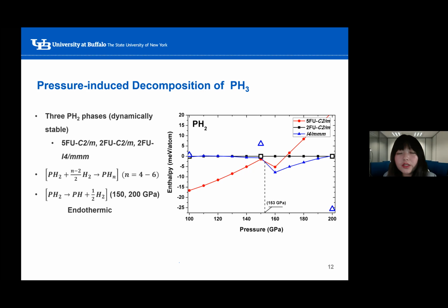So from our evolutionary search, we identified three dynamically stable PH₂ phases, including a 5 formula unit C2/m phase, a 2 formula unit C2/m phase, and an I4/mmm phase. More importantly, the formation of PHn from PH₂ and hydrogen at all pressures, and the decomposition of PH₂ into PH and hydrogen at 150 and 200 GPa are both endothermic. So for the three PH₂ phases, below 153 GPa, the 5 formula unit C2/m structure is the most stable one, excluding zero-point energy. Above 153 GPa, the 2 formula unit C2/m and I4/mmm become preferred.